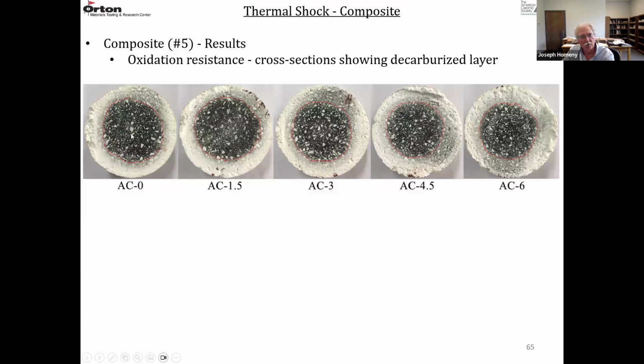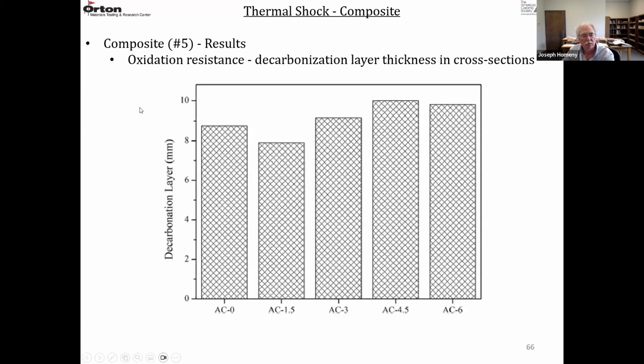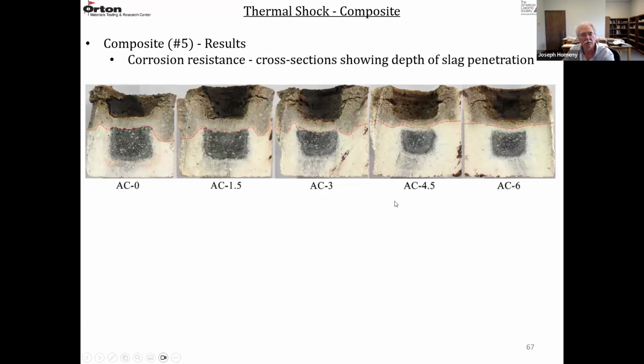So as you go from no composite powder addition to AC6, which I think was 12%, there's really no difference in the oxidation. So this is a plot of the decarbonization layer in millimeters versus the 5 different compositions. And they're all around 9 to 10 millimeters. There's not a great deal of difference in the oxidation. But apparently there was a significant difference in the corrosion resistance.